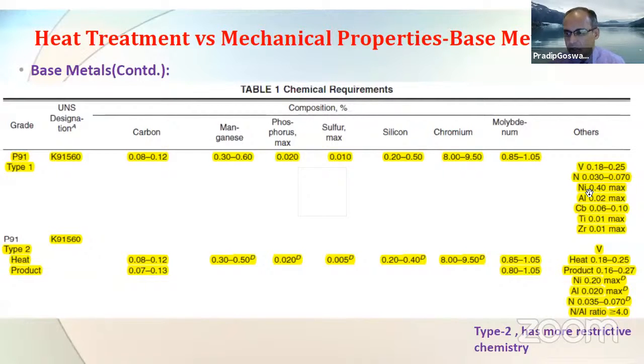But when you see the residual, so-called residual alloying elements, you see here that type 2 generally has a lower nickel content as compared to type 1. Aluminum is the same, right? But here it talks about one ratio called nitrogen to aluminum ratio. It should be typically more than 4.